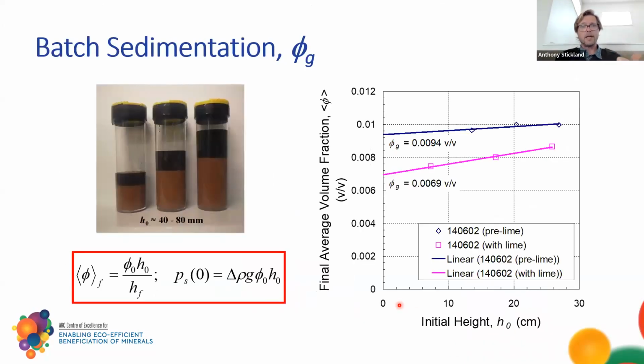So that's filtration testing. For sedimentation testing, we can use a very simplistic idea. If I sediment a material, the concentration at the top of the sediment is at the gel point. There's no pressure acting on it. But as I go further and further into the bed, the concentration goes up because of the weight of the particles sitting above it. If I wanted to measure the gel point, I can't do a test where I have zero initial height. It's impossible. So what you need to do is have a series of tests, either increasing concentrations or increasing initial heights, and then extrapolate back to a zero initial height, which is what these results here are showing.